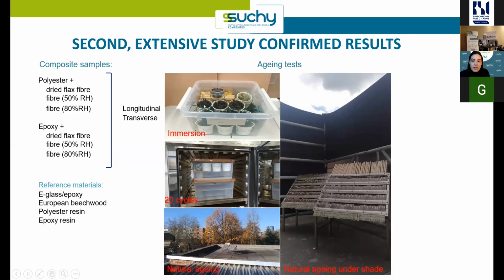So we also did full immersion tests, and then we increased the cyclic behavior that I was just talking about to 20 cycles. And we also did outdoor aging in the full sun and also in the shade to rule out the effect of just the UV. So there's a lot of data, and I'll just highlight a few things because otherwise I need a whole PhD presentation and that would be too much.